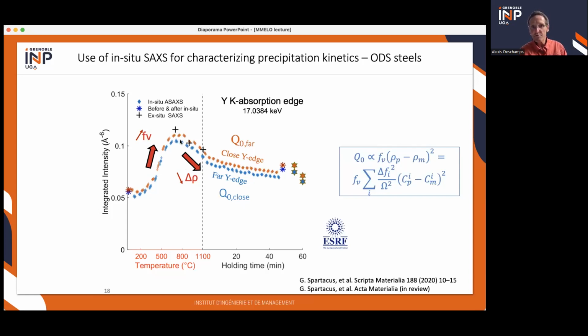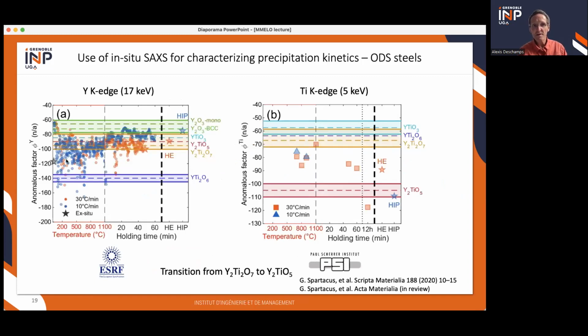And you always have a difference between the two energies that you probe, one far from the edge in blue and one close to the edge in orange. And this contrast tells you that you have yttrium within the particles. And by knowing the intensity change between these two, you can try to calculate how much yttrium you have. And so you can do that. You have the in situ data, so a lot of data, a bit noisy because it's very, very small differences between the two intensities. And you can calculate what we call an anomalous factor